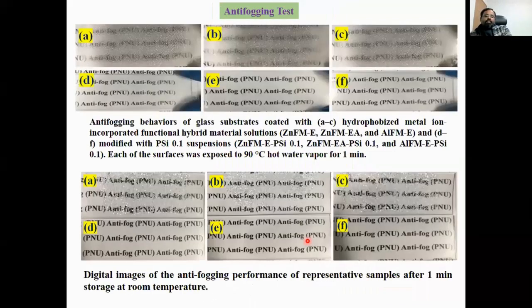And further, we checked the anti-fogging properties on the coated substrates, the hydrophobic coating and the super hydrophilic coating. We did the anti-fogging test using a hot water bath. We kept our coated substrate over the hot water bath, at a water bath temperature of around 90 degrees.